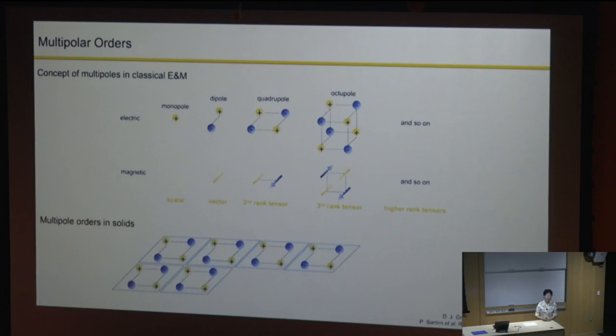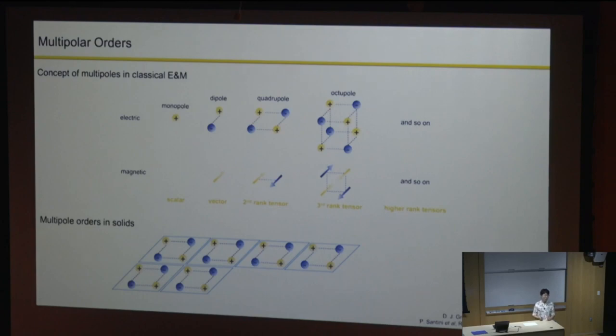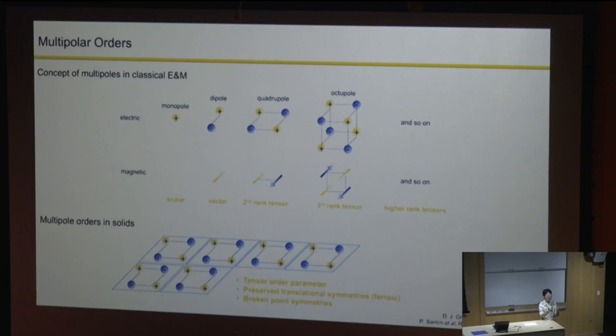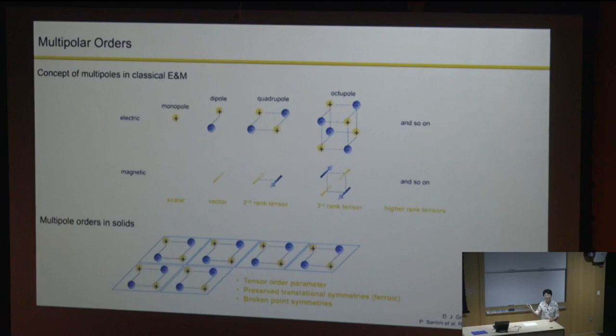What's problematic about this? Imagine a square lattice with an electric quadrupole inserted in a ferroic way. This pattern does not break any translational symmetry because it repeats exactly in every square. So when people use diffraction techniques to measure this, they face a lot of challenges because there are no new peaks due to the absence of translational symmetry breaking.